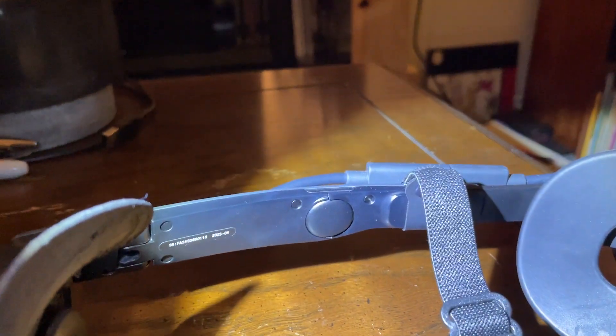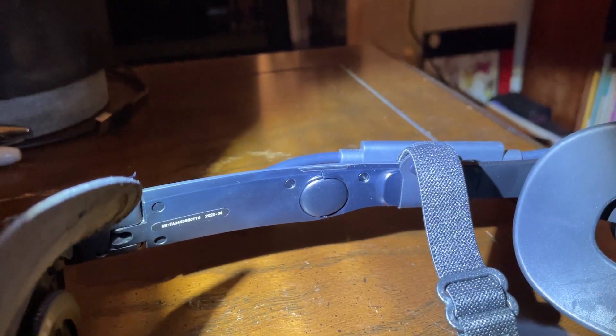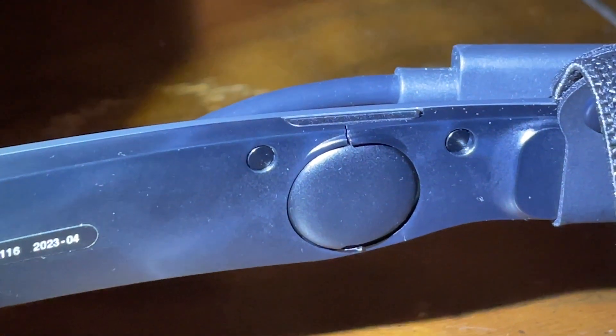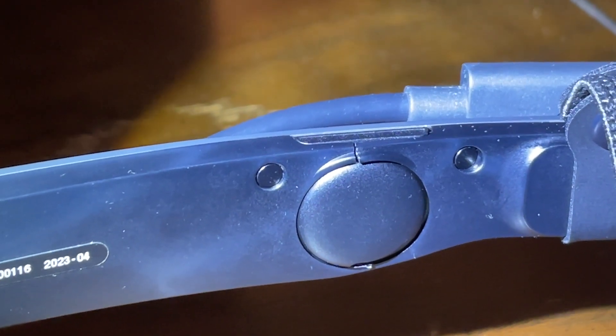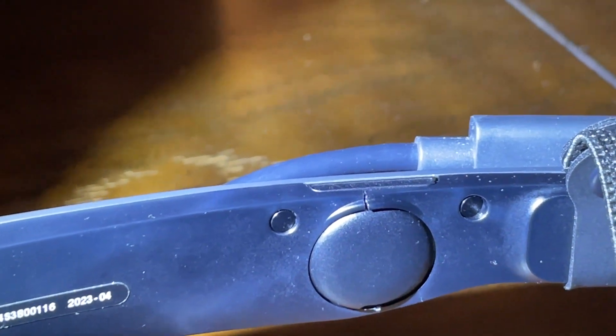The original run of this has a defect in the side braces. This piece of plastic is really cheap — they do sell official parts on iFixit. They didn't make that little reinforcement ring around that section big enough, so it actually ends up cracking. The developers mentioned that the plastic in the injection molding meets right at that point, and they needed to make it thicker. After a few months, they did make it thicker.